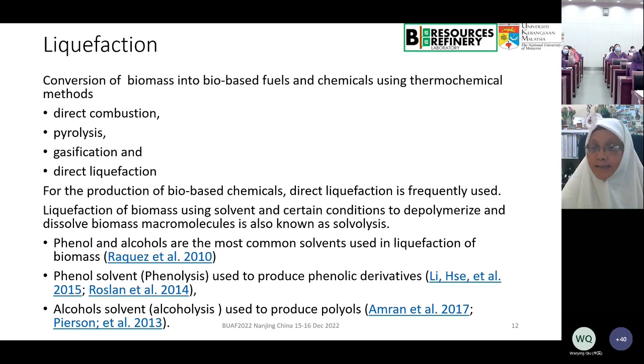The most common solvent depends on what end product you want. If you are making phenolic resin, then phenol is one of the best. But if you are targeting lots of polyol for making polyurethanes and so on, the alcohol solvent is the best choice. So it depends. When you use phenol as solvent, it can produce a lot of phenolic derivatives. And when you use alcohol solvent, or alcoholysis, you can produce as much polyol as you need, and polyol is very important if you're targeting it to react with isocyanates and so on.